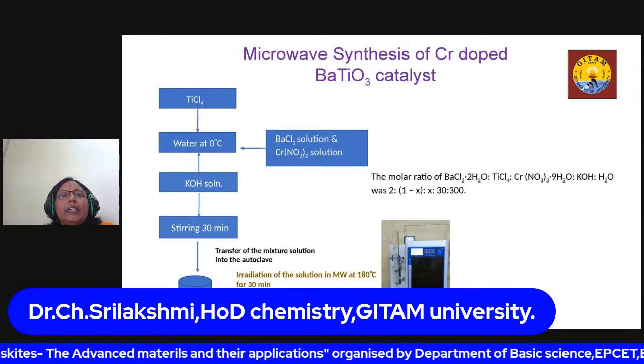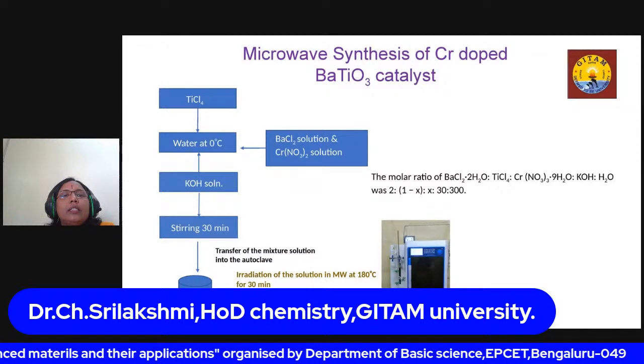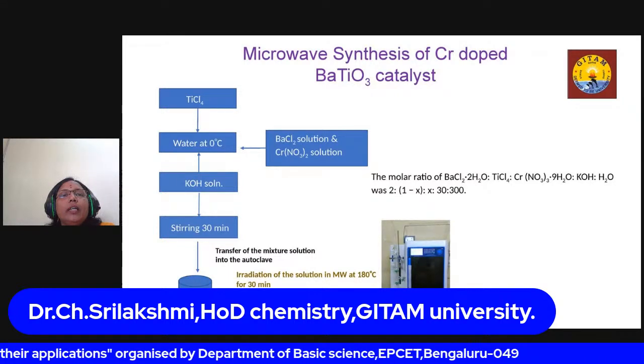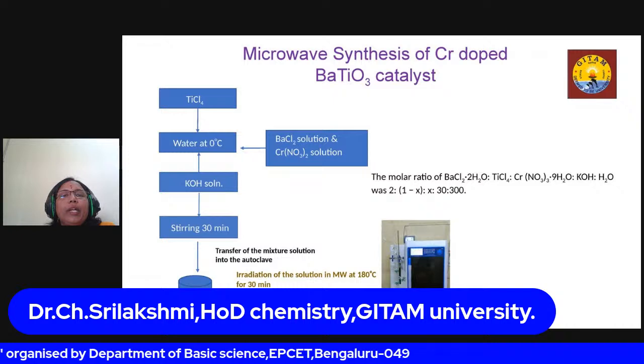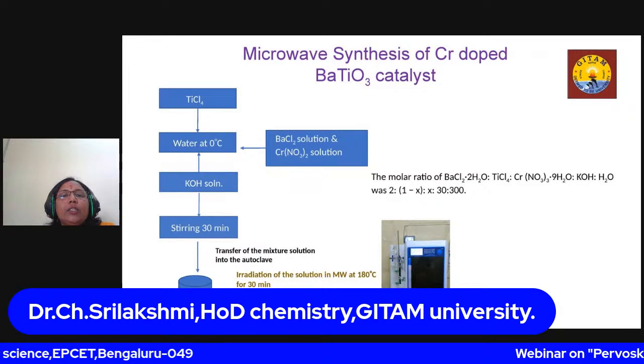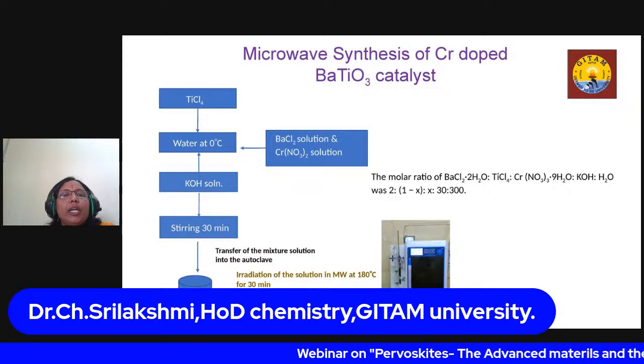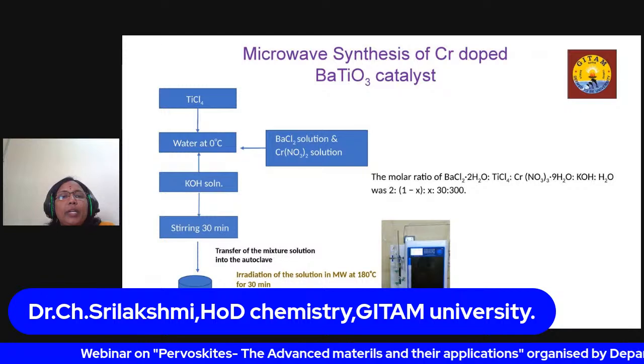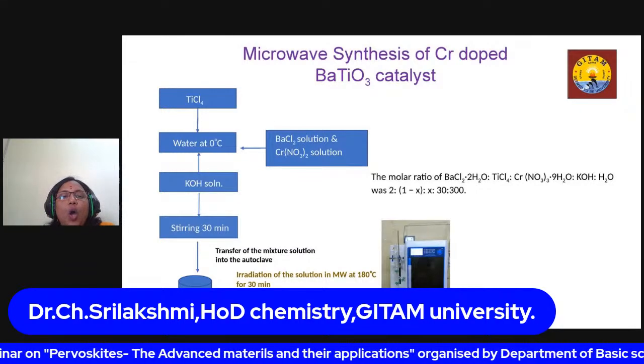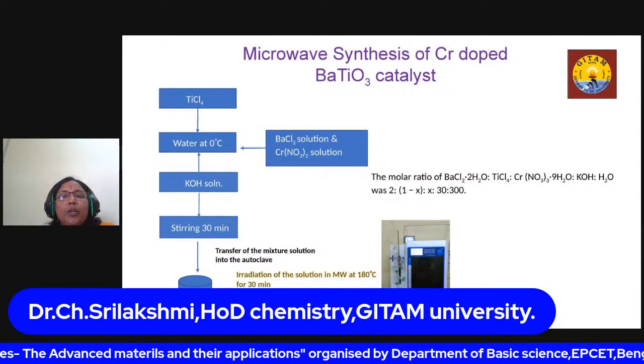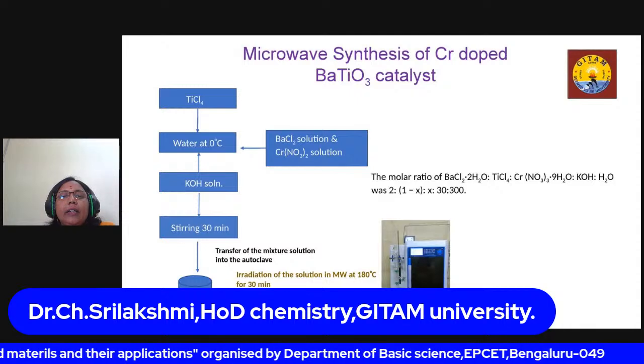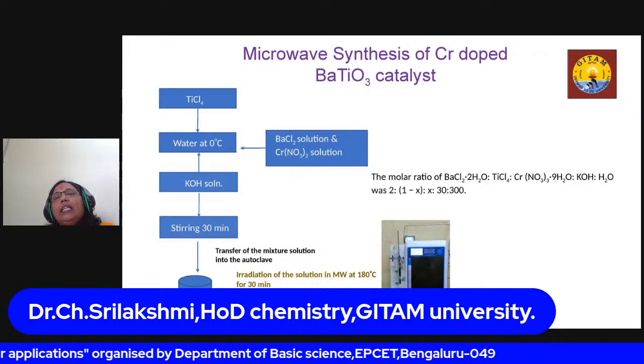First, titanium chloride is dissolved in water at 0 degrees. Later, barium chloride, chromium nitrate, and KOH are separately dissolved in deionized water and mixed into the titanium chloride solution. The resulting mixture stayed for 30 minutes at room temperature, then was transferred to the autoclave, placed in the microwave, and irradiated at 180 degrees for 30 minutes.